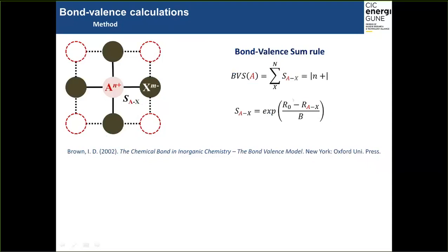Yes, requiring that the sum of all the bond valences connected to an atom equal the absolute value of its oxidation state. And the bond valence can be calculated with this expression shown here on the screen, where R0 and B are empirical parameters, while R refers to the distance between the two ions, the cation and the anion. And both R0 and B can be fitted from known crystal structures.